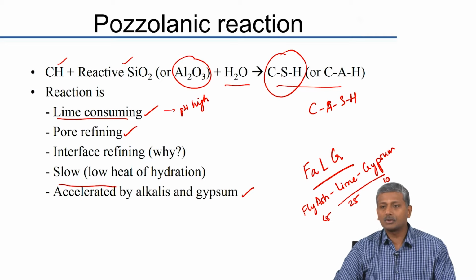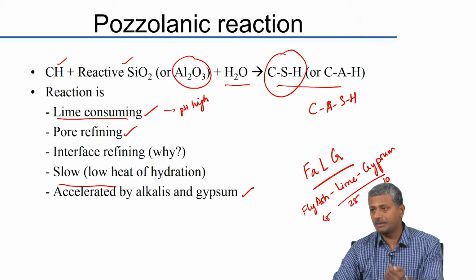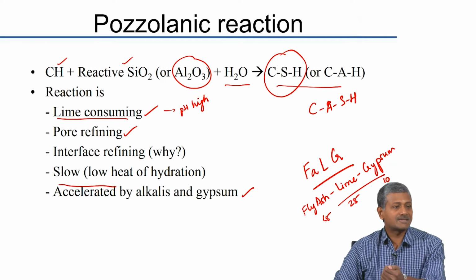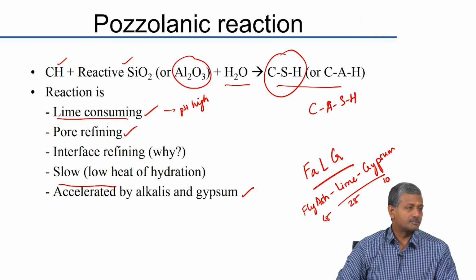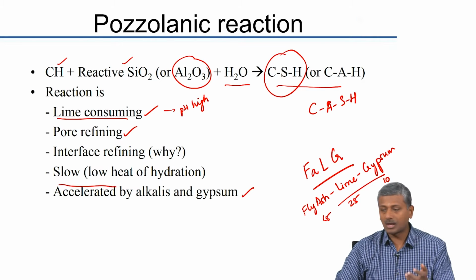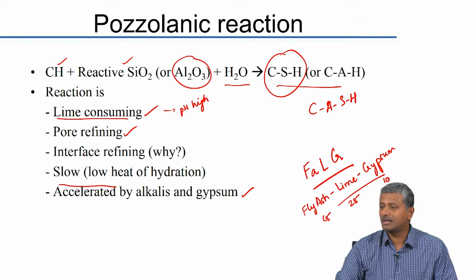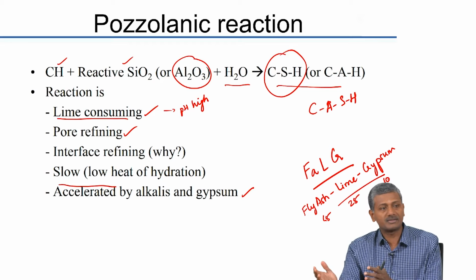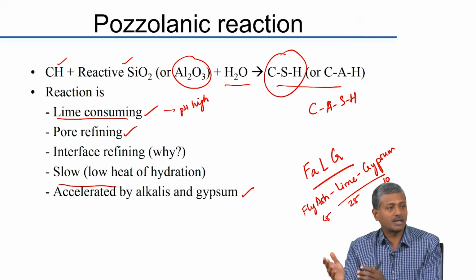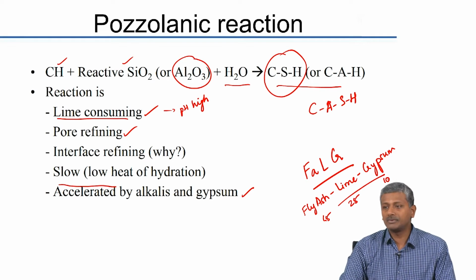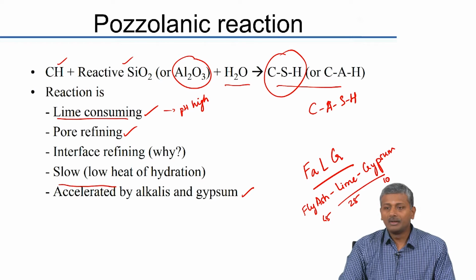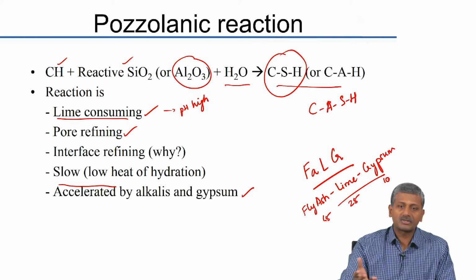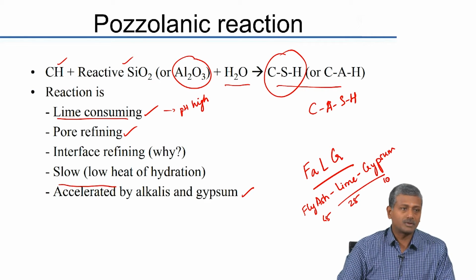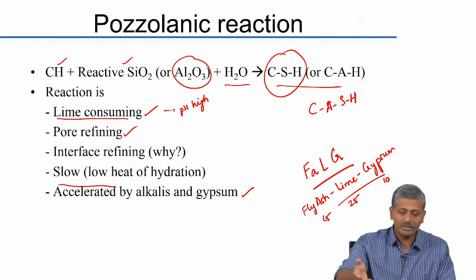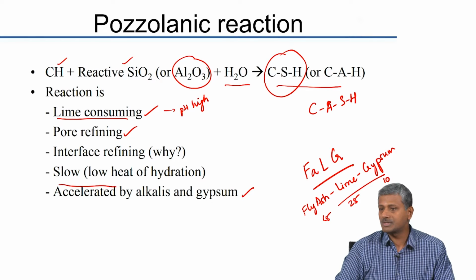So, what happens here is you are relying on the reaction between fly ash and lime, and that reaction is accelerated by the presence of gypsum. Okay, just like what happens in a cementitious system, here you have taken it out of cement, there is no cement in this case, you only react the fly ash with lime and accelerate that reaction with the presence of gypsum. Okay. So, you end up obviously forming a structure like CSH and so on, because the reactive silica from fly ash will react with the lime to produce CSH.